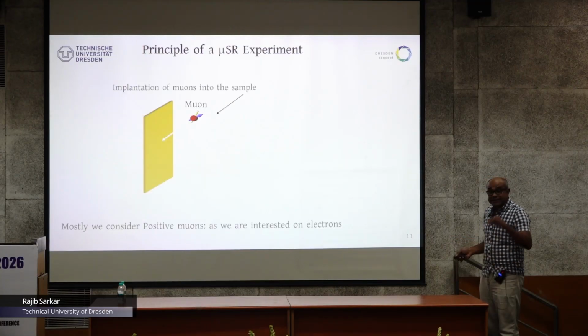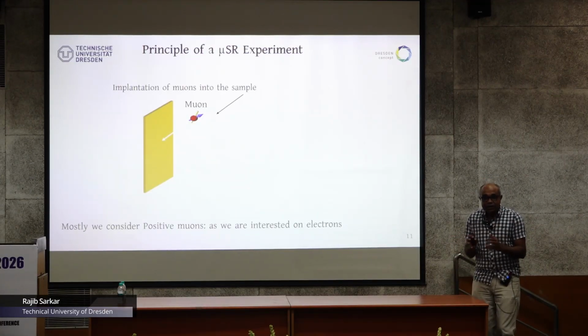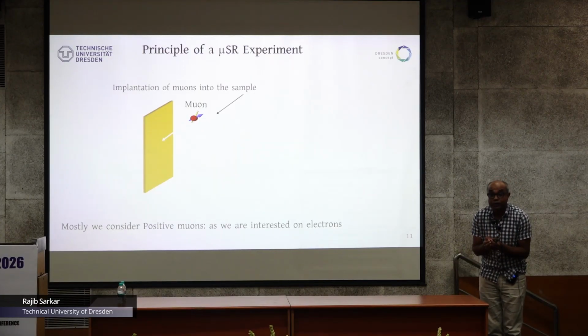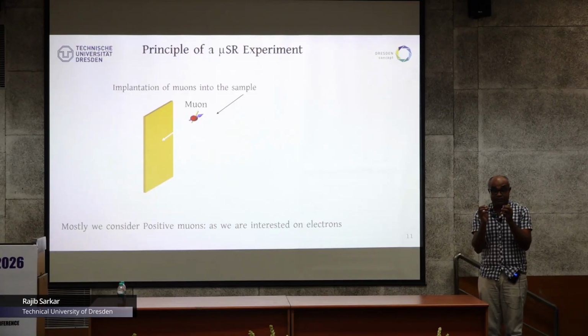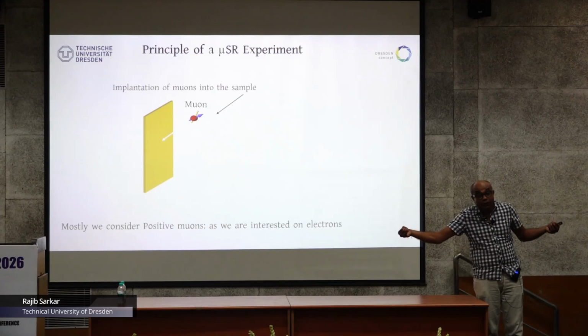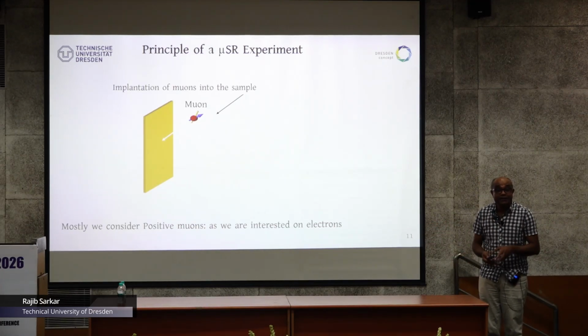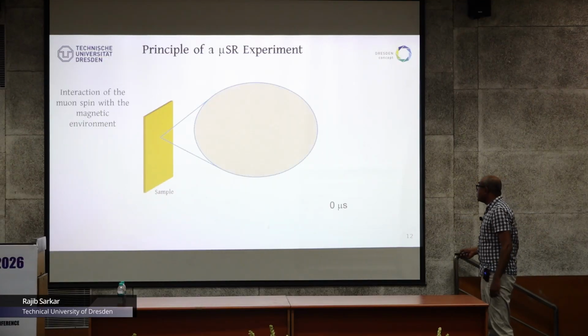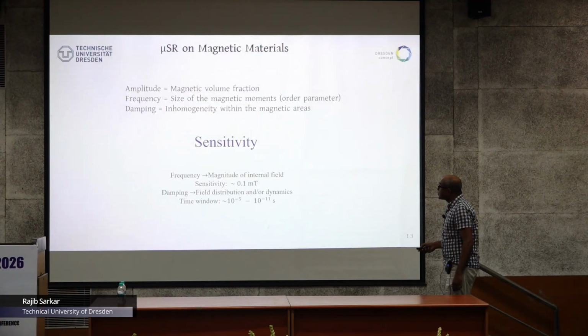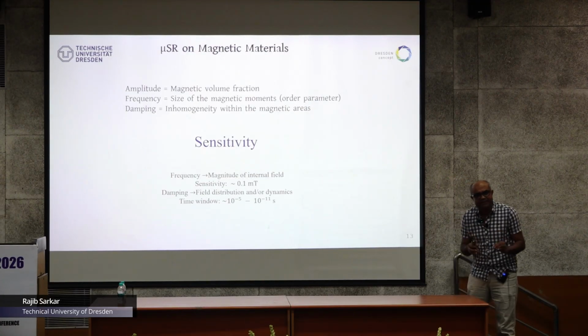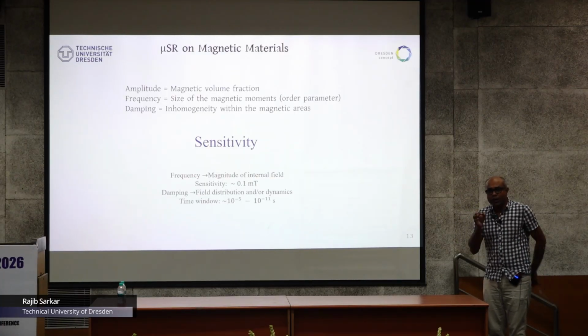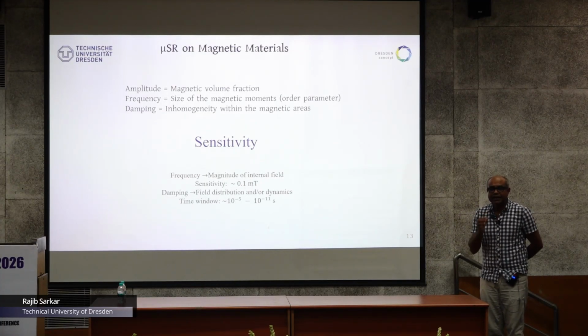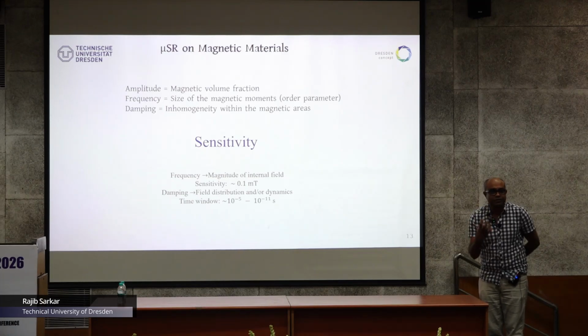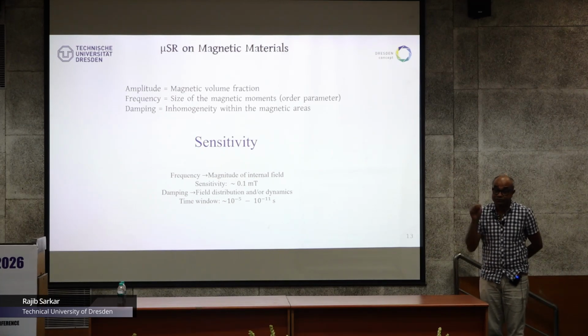And what it usually does, it is actually implanted into the sample, and sits close to the electron if you are really using the positive muon, okay? And then senses what is happening around, in particular the internal field and the fluctuations of the electrons, and then decays into a positron. And that actually carries the information. So that means it is not perturbing, not disturbing anything in the system, but carrying the information to a detector. This is how the muon works. So I think this is a very sensitive measurement, and expensive also. So therefore one should do muon experiments when you really want to know a very tiny internal magnetic field presence, or what is the level of the fluctuations your spins are doing. In that case, the muon is very, very sensitive.